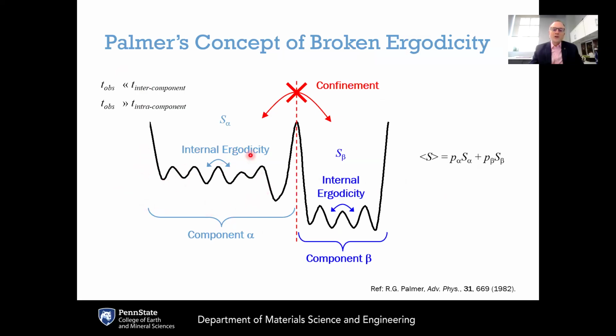And you've got a group of microstates here on the left with really small activation barriers between those microstates. That is defined to be one of the components, component alpha, because within that component alpha, the barriers are very small, which means that the time scale for exploring different configurations within the component is fast. Then there is a second component, component beta on the right, because within this component, the configurations are also easily accessible within the component. However, there's a very large barrier between the two components, which means that the time scale for transitions between components is extremely long.